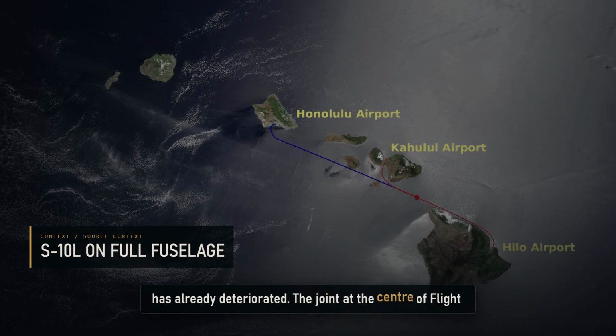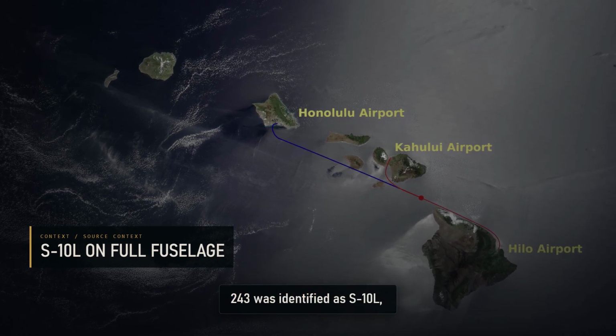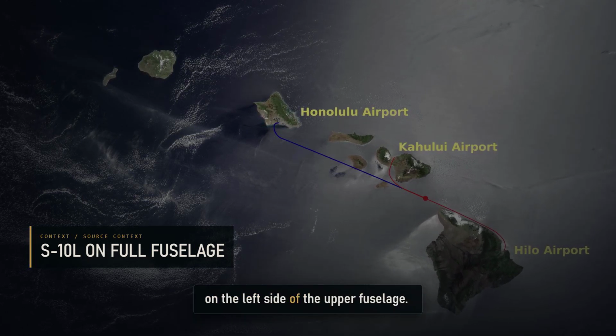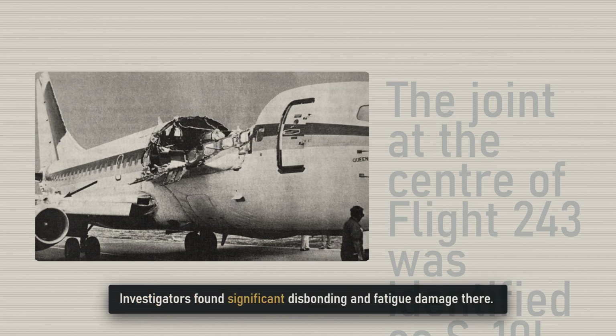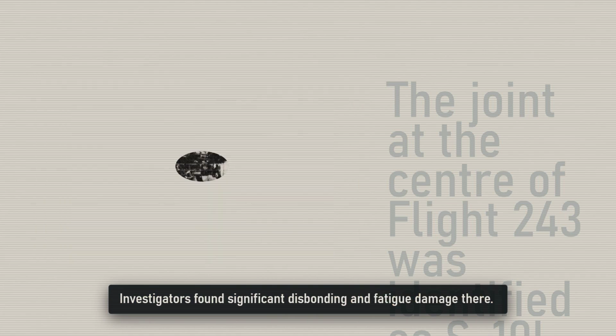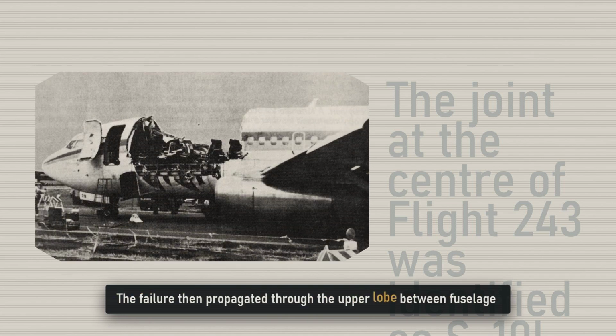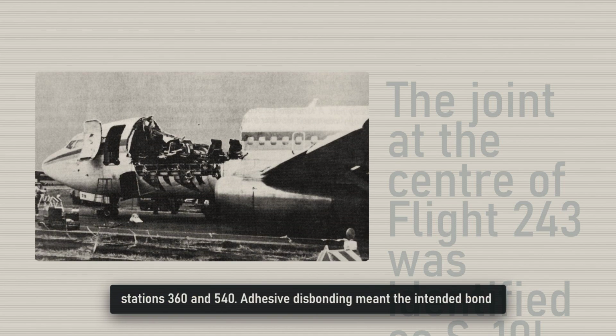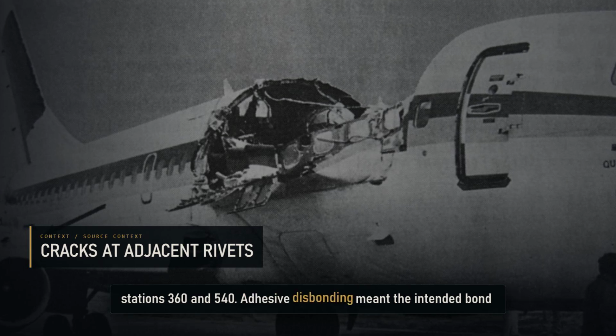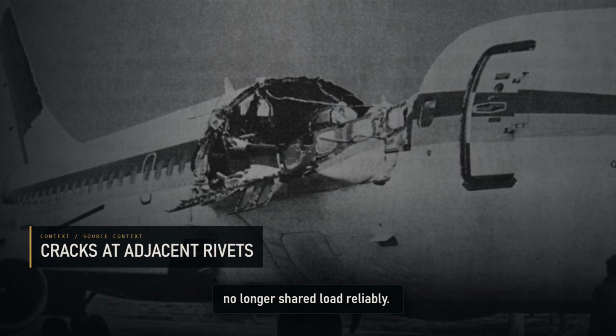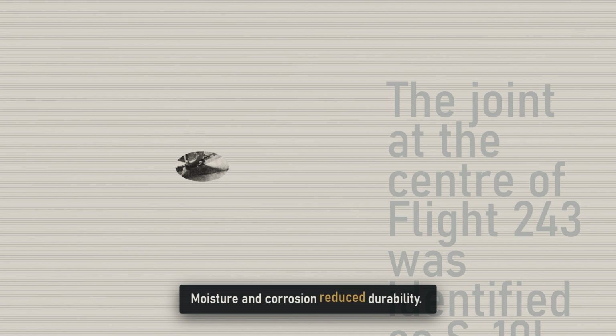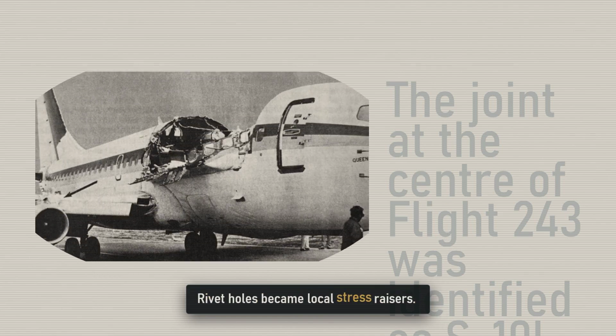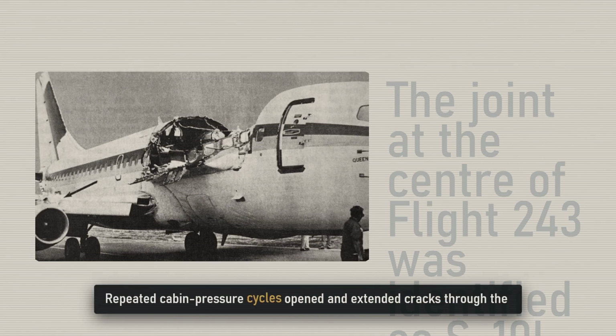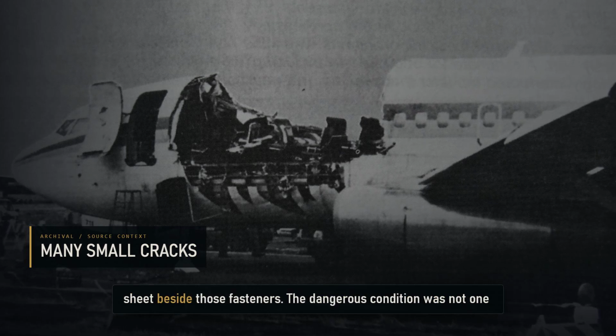The joint at the center of Flight 243 was identified as S10L on the left side of the upper fuselage. The designation located a longitudinal seam. Investigators found significant disbonding and fatigue damage there. The failure then propagated through the upper lobe between fuselage stations 360 and 540. Adhesive disbonding meant the intended bond no longer shared load reliably. Moisture and corrosion reduced durability. Rivet holes became local stress raisers. Repeated cabin pressure cycles opened and extended cracks through the sheet beside those fasteners.